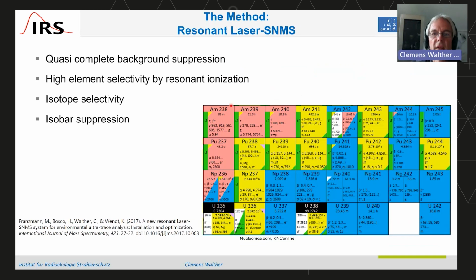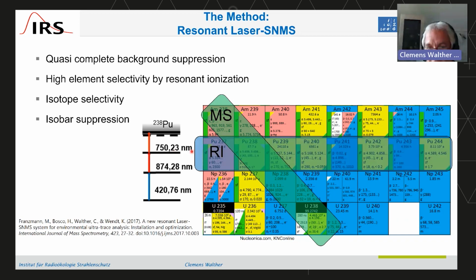So the method we use for that is the so-called resonant laser SNMS. You see here part of the table of the nuclides, and if you do the mass spectrometry, you can single out just one isobar. All of these isotopes have the mass 238. If you now apply a selective ionization process, you can single out just one element, and that gives you the plutonium-238, which satisfies the 238 isobar condition and being a plutonium element.